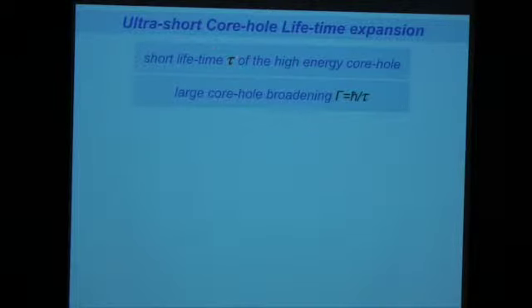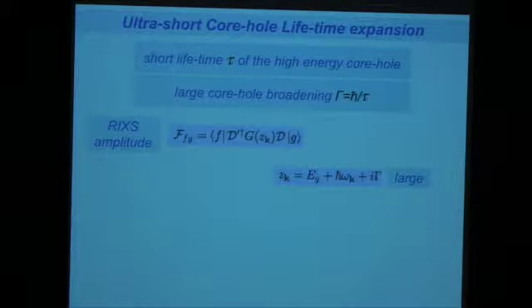So we have to remember that there is a short lifetime tau of this high energy core hole in the intermediate state. I make this core hole, and actually it will tend to decay by lots of different processes. It can Auger decay, another inner shell electron can fall in, kicking out another electron, and actually it can fluoresce in many different channels. So it's very unlikely it does this RIXS process. It's much more likely the core hole has disappeared by another scattering channel before the electron that was up there can fill it again. So that makes the core hole very unstable. It lives for a very short time, which means that in the denominator I have a large core hole broadening, this gamma, which is basically 1 over the core hole lifetime. So maybe I can use that.